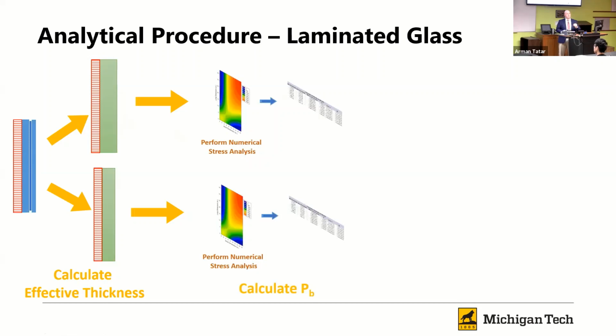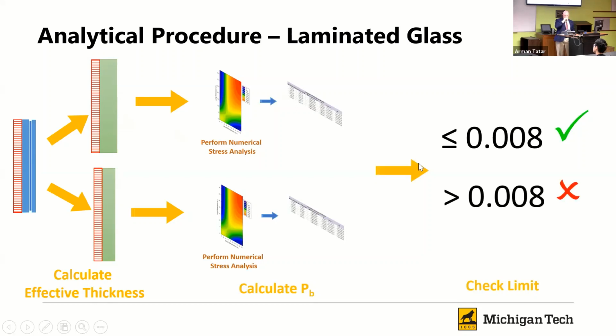We plug that into our whiz-bang spreadsheet to do the glass failure prediction model, and then we're going to use the principle of weakest link here: whichever one gets to 8 in 1,000 first is the one that limits our design. And so we're just going to take the largest of these two probabilities of breakage, and make sure that is less than or equal to 8 in 1,000. If either one of them happens to be larger than this, then we have to make a change in our construction because one of the plies doesn't meet the requirements.